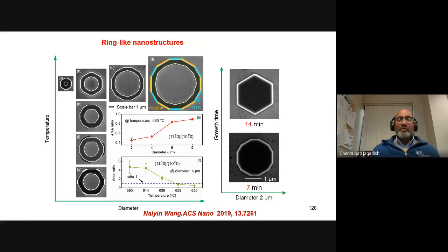And then once you really open the ring, you can see these alternating facets, and you get a beautiful ring-like structure here. If you keep on growing, the middle also gets filled up. And then ultimately you end up finishing off with this nice, beautiful, hexagonally faceted nanomembrane, which is very good for nanomembrane lasers and MEMS applications and a range of applications.